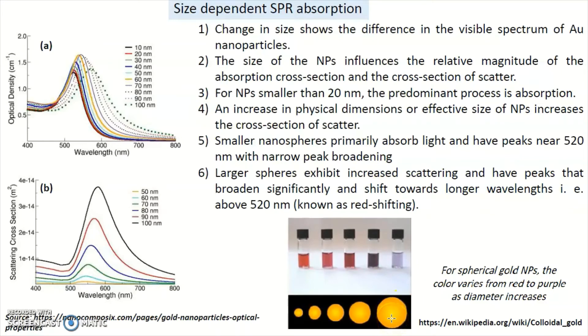Therefore, you have to balance scattering and absorption. If scattering is higher, absorption is lower. If absorption is higher, scattering is lower. In case of smaller gold nanoparticles, absorption is higher and scattering is lower. But in case of bigger nanoparticles, absorption is lower and scattering is higher. Because of this change in absorption and scattering, you observe a change in color.